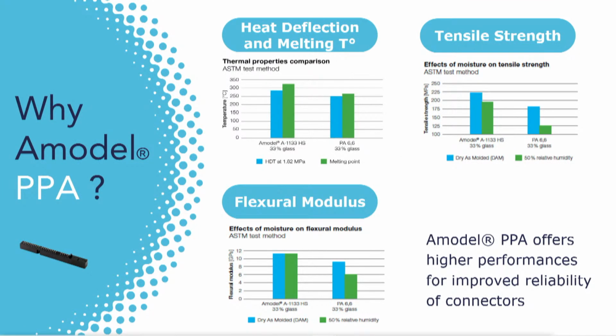But let's go a bit further. More important, tensile strength. PPA starts higher than PA66. Here we're talking about 225 megapascal, and more, dry as molded. And more important, it keeps this tensile strength even in a humid environment. Here, for example, you can see 50% relative humidity. At 50% relative humidity, PPA retains roughly 90% of its tensile strength. In comparison, Polyamide 6.6 starts lower, at 185 megapascal, and loses 60%, about two thirds, of its tensile strength when exposed to humidity.